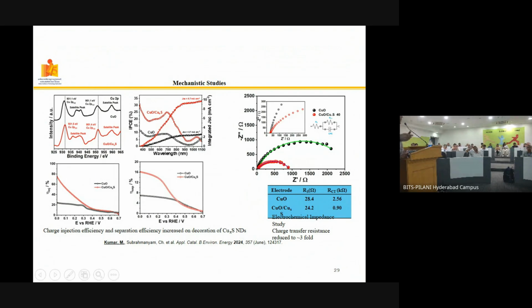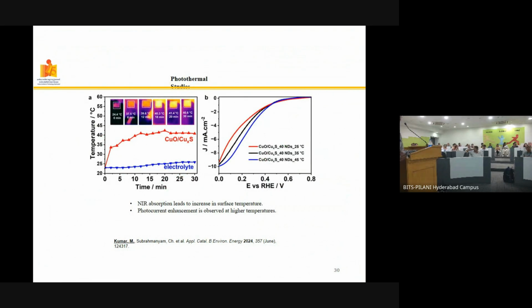That means this can possibly be due to some kind of selective poisoning effect. If you really want to look at it, as I mentioned, this has an absorption in the NIR region. It clearly tells that the catalyst, or the electrode, is active, and NIR absorption leads to increased surface temperature.